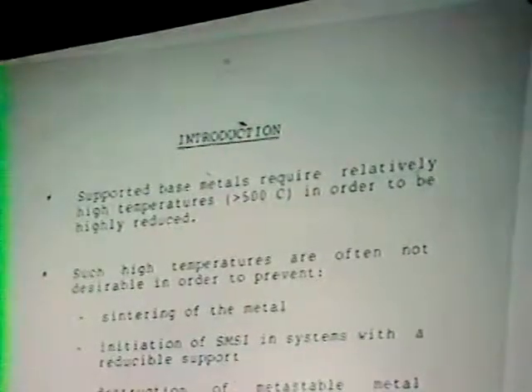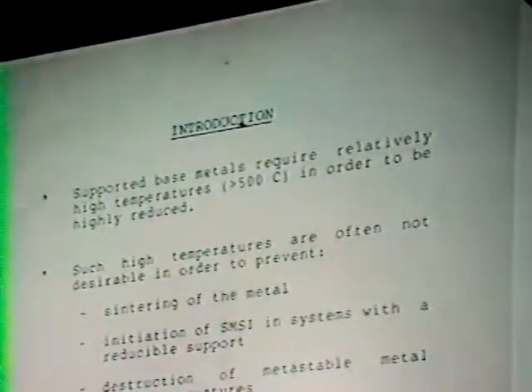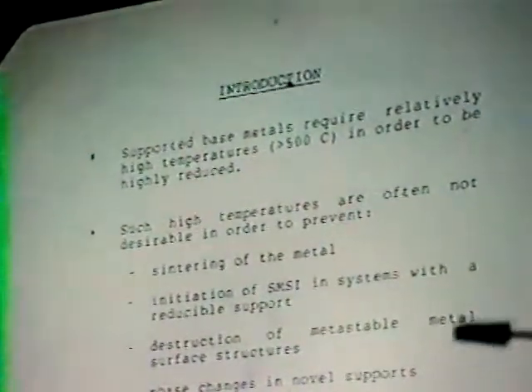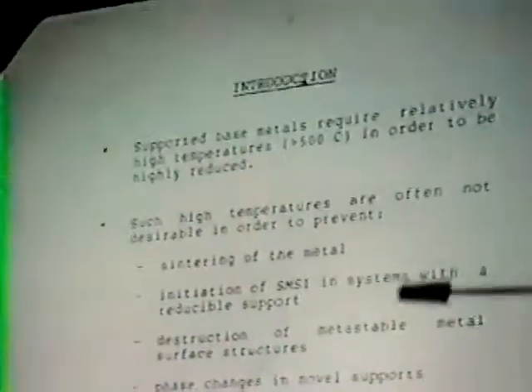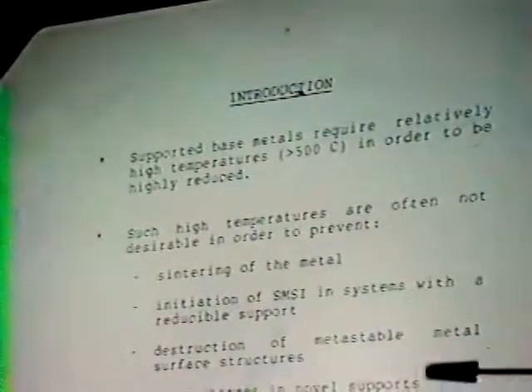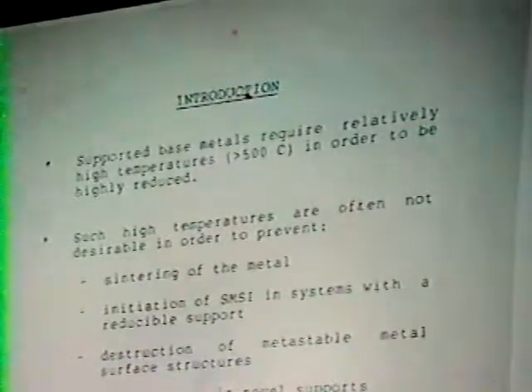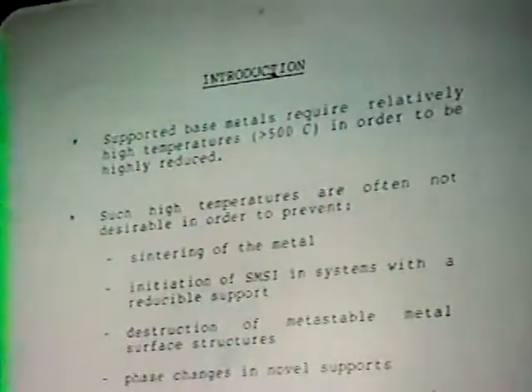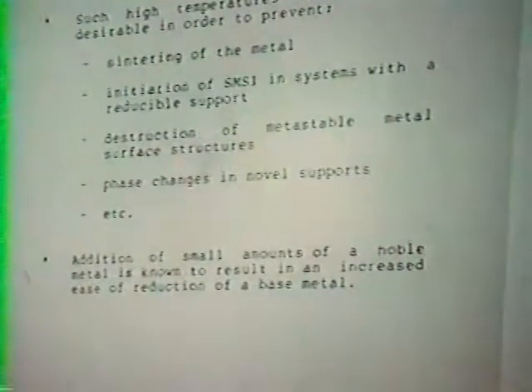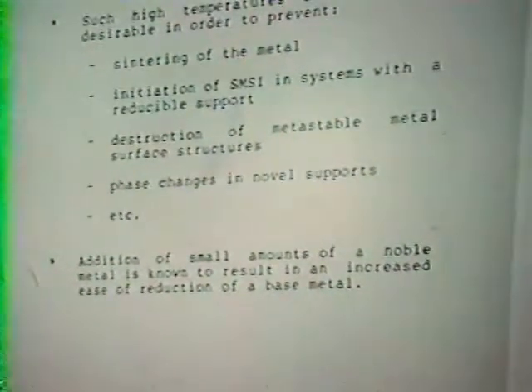Typically, supported base metals especially have a very high temperature required for reduction, greater than 500 degrees centigrade often. And such high temperatures can easily result in such deleterious effects as sintering of the metal, initiation of SMSI or other types of metal support interaction, destruction of metastable metal surface structures that may be derivable at low reduction temperatures, as well as possible phase changes in dealing with some of the new novel supports being tried out and utilized.